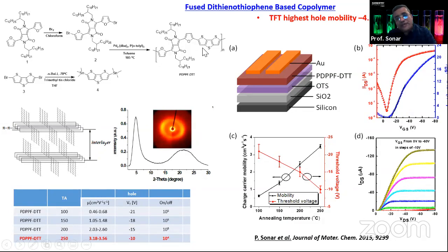But again, you have to compensate with alkyl chains, because if you put in too long a fused backbone, then your polymer becomes like a rock and you can't make a solution out of it. So we need to add a long alkyl chain to make them solution-processable inks, and then we can print them or spin coat them. The on-off ratio values and the mobility values are shown here.